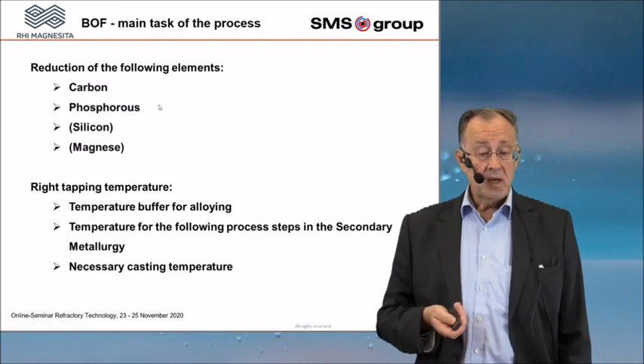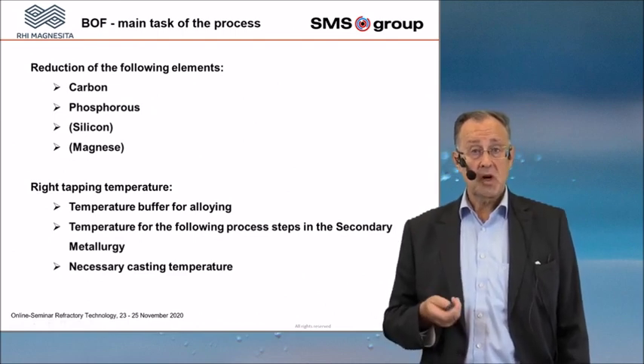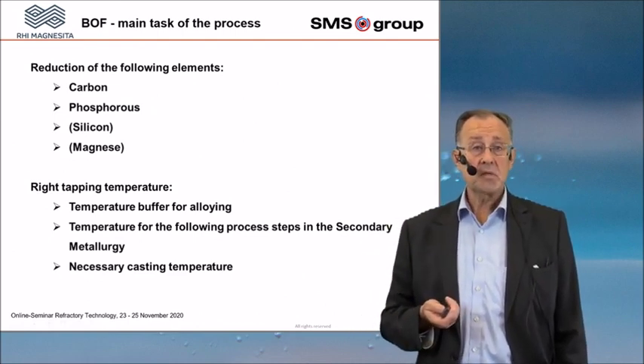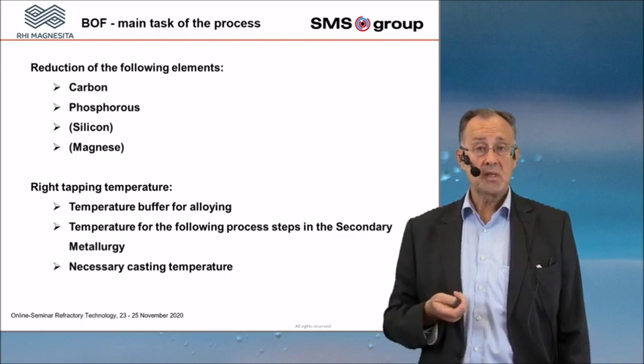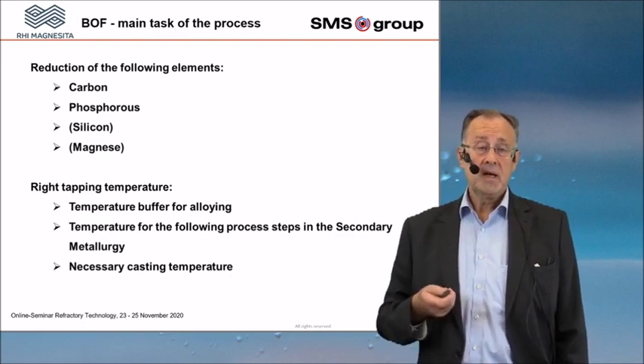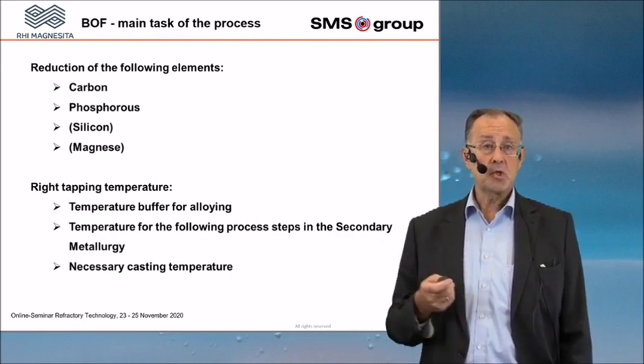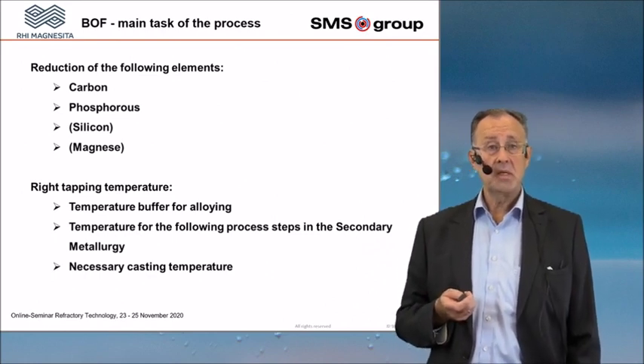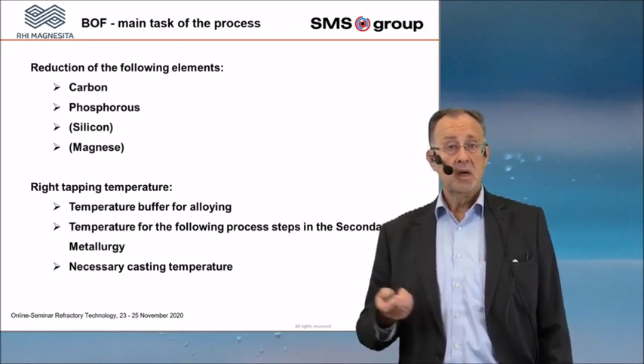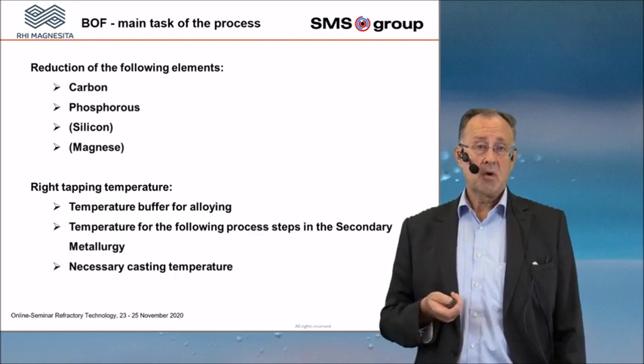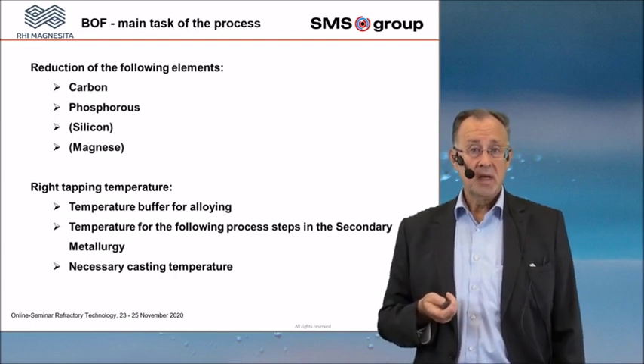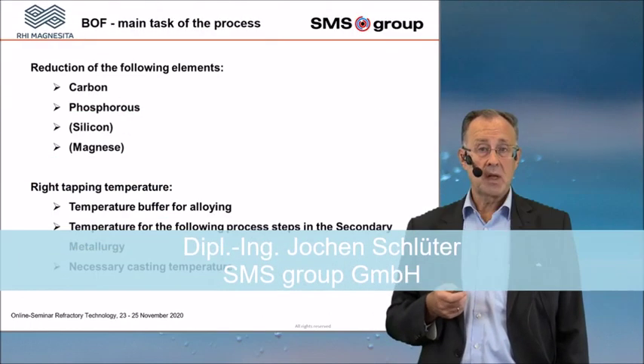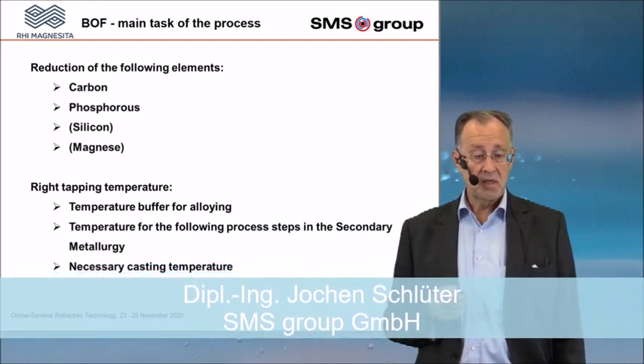Okay. At first, you have to reduce carbon. Carbon is coming from the blast furnace, from the reduction process inside the blast furnace. And the hot metal is, depending on the temperature, saturated with carbon. That means you have to bring out the carbon, and the carbon value is around about 4.5% inside the hot metal. And so that means you have to oxidize the carbon.